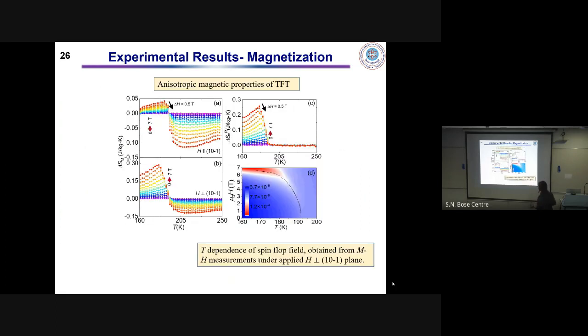This magnetization curve also hints that there exists a magnetic anisotropy in this system. Now, in order to clarify that, we have studied the anisotropic magnetic property, and we have calculated the isothermal magnetic entropy change in both directions. If we subtract these two, the difference of the two isothermal magnetic entropy changes gives a finite value, which confirms that there exists magnetic anisotropy in this system. We have also seen that the peak position shifts towards low temperature with increasing field. These M-H and entropy curves hint at a possible existence of spin flop in this system. And here you can see the temperature dependence of the spin flop field, which is obtained from the M-H measurements when the magnetic field is applied in the out-of-plane direction.